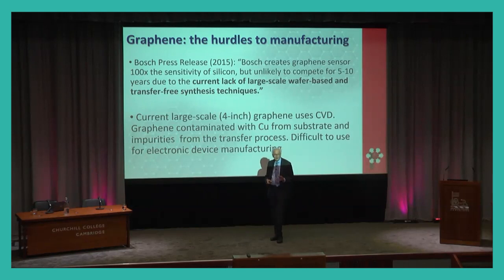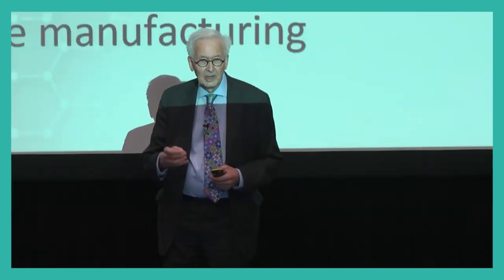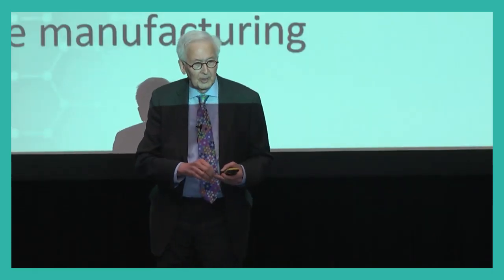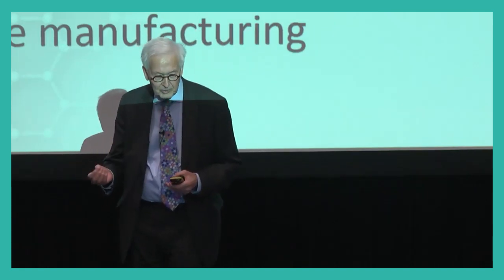And in chemical vapor deposition, you can grow graphene 4 inches in diameter or maybe 6 inches in diameter. But to do this, you have to have a catalyst to decompose the growth gases. And this is typically copper. So you deposit graphene on the copper, and then the copper atoms contaminate the graphene. So it's contaminated graphene. And then to make the graphene useful, you have to take the graphene off the copper and put it onto a more useful substrate.